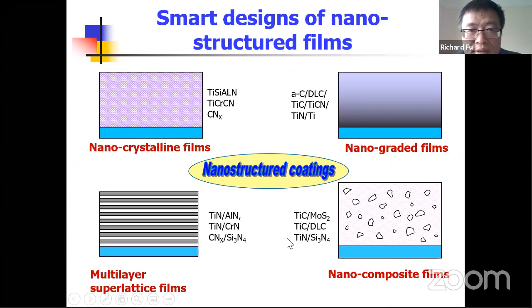So in order to achieve high performance of the coating and thin films, there are different designs. If we simply reduce the size, then we can achieve hardness, but the crack easily propagates through the materials, and the coating still has low toughness. That's why we use different designs, for example, nano-graded films. The coating from the top surface gradually changes layer by layer, nano layers of the material, graded changing the different type of coating until the substrate, which can increase the crack propagation resistance and also enhance the material load bearing capacity.